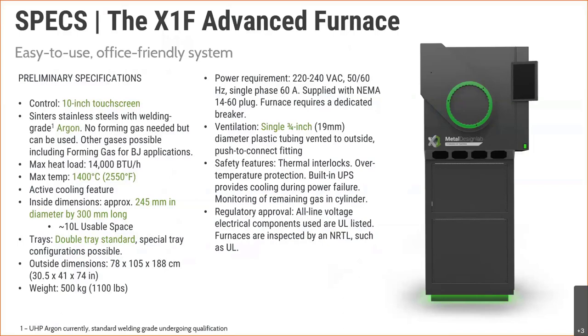So once you tap that button to indicate what material you have in the furnace that you're trying to sinter, either 14 or 16 hours later, respectively, of the material that you've chosen, you'll have a fully sintered, fully dense metal part north of 97% density. You can see the sintering temperatures are certainly for ferrous alloys. And the sintering chamber is a cylinder that's a little more than 9 inches in diameter and just about a foot deep. So it can certainly accommodate any size part that you build, either whole or if you're doing multiple parts, where you can also have multiple shelf configurations or single shelves.